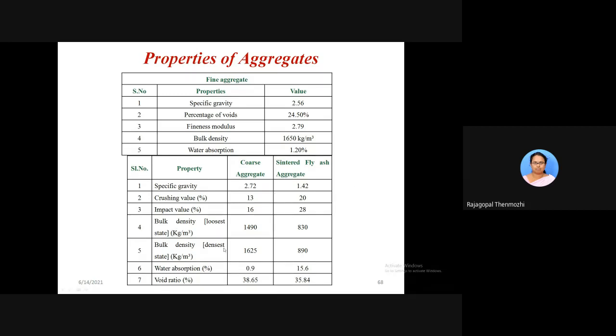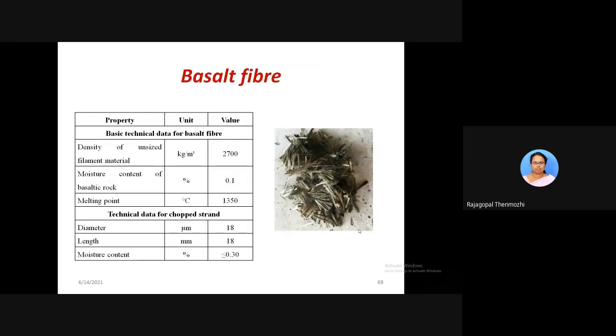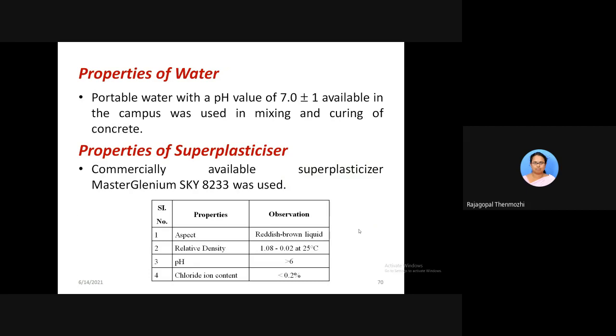The bulk density here is 1625 kg per meter cube, whereas for the sinter fly ash aggregate, as it is very light in weight, we have got only 890 kg per meter cube. This weight reduction leads to saving of weight on the foundation, so the cost could be saved. These are the properties of the basalt fiber and the properties of water and superplasticizer. What we have used is MasterGlenium SKY 8233.